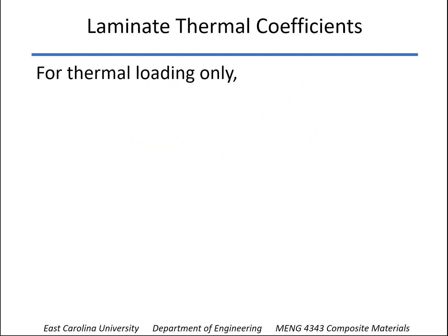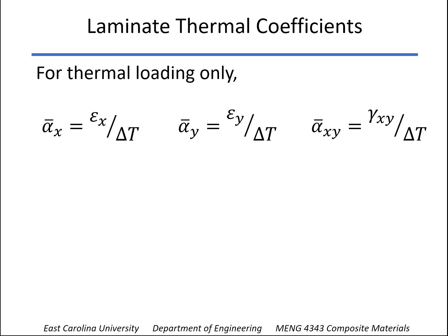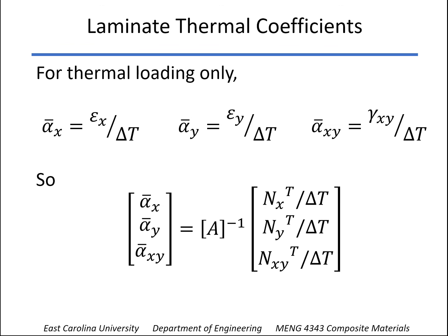And from that, if we have thermal loading only, then we can calculate the laminate's thermal coefficients by taking the strains, again, just due to thermal loading, and for each one of those dividing by delta T. I've used a bar over the alpha x, alpha y, and alpha xy to show that they apply to the entire laminate instead of an individual layer. So we can also write that out as shown here. The alpha coefficients, the laminate thermal coefficients, based on the A inverse matrix and the thermal loadings.